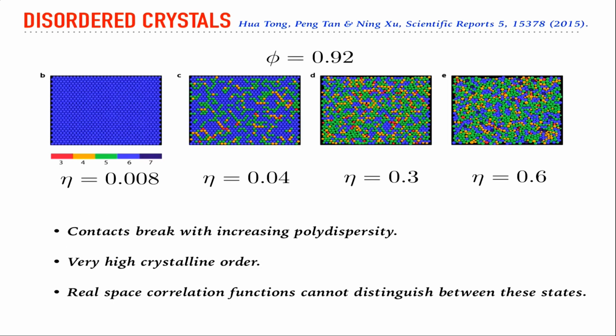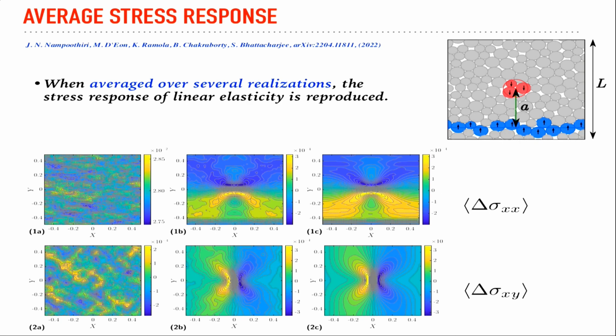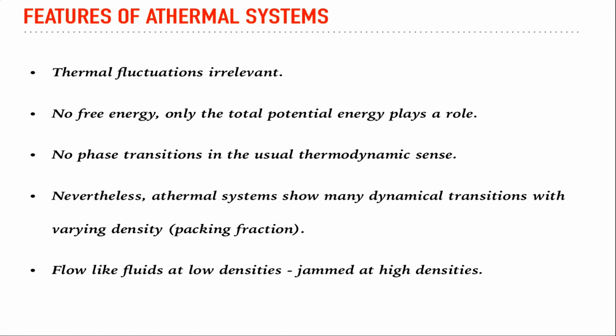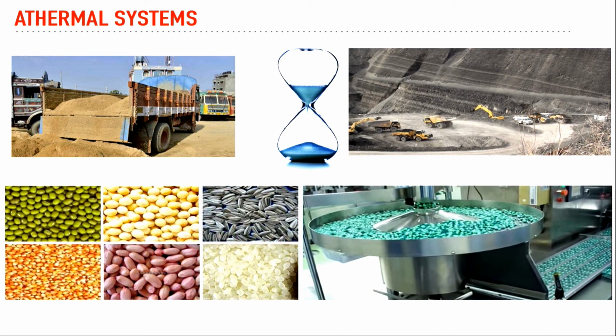But even more directly, you can define a phase transition as follows. You can ask, is this flowing or is it jammed? Now that is a direct measure, a discontinuous change in, let's say, the dynamical properties of the system. If I close this point here, which is some sort of control parameter, none of these particles move. If I open it, they move. So that's a clear discontinuous change as you tune a parameter in the system. By the size of the hole that is allowed, you have a discontinuous change in the dynamics of the system. So that is also a phase transition, but not in the same manner that you would describe, let's say, a magnetic phase transition.